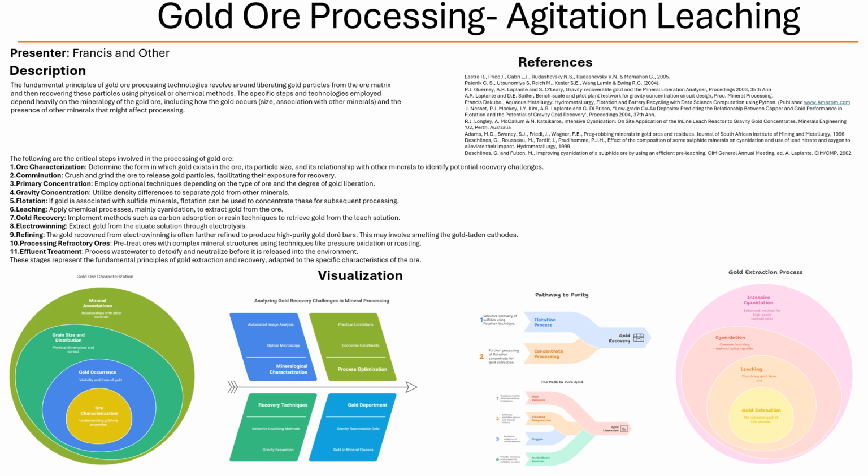Oh, okay. Like what? Well, for example, they talk about how cyanide reacts with oxygen to form cyanate, which is a less toxic compound. But cyanide also reacts with various sulfur compounds in the ore, forming thiocyanate, which is a major consumer of cyanide. So you can actually lose cyanide during the process. You can. And that's why it's important to monitor and control those side reactions.